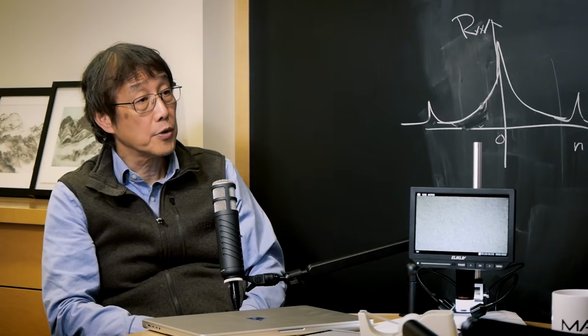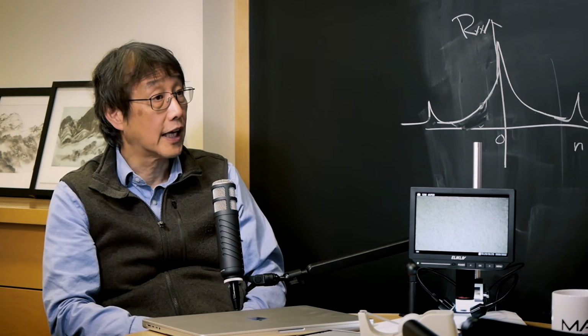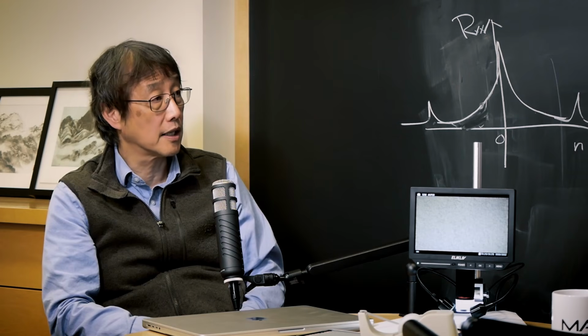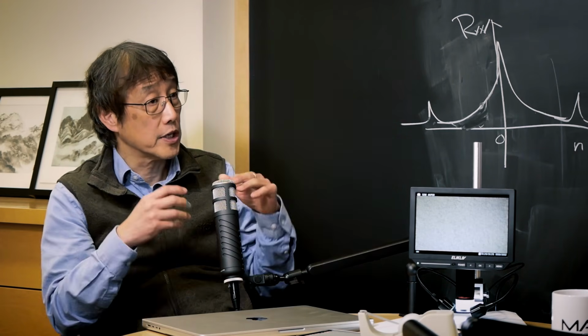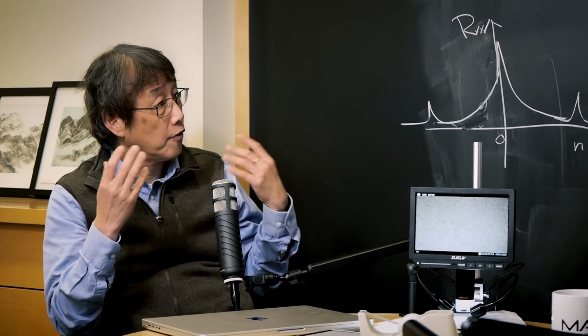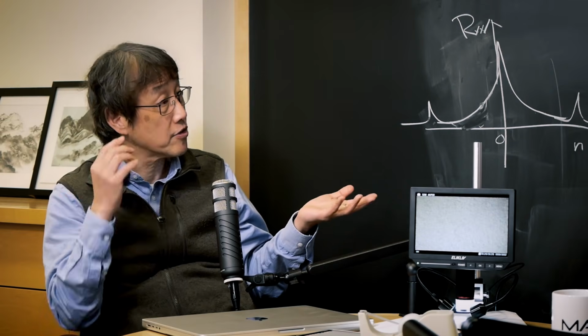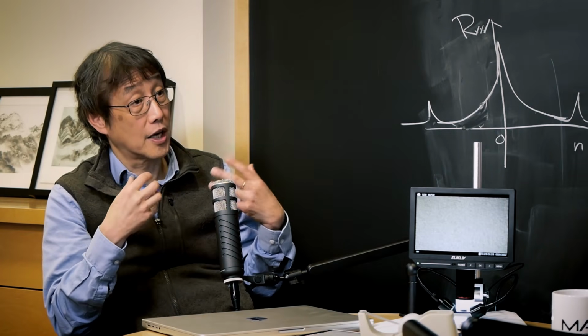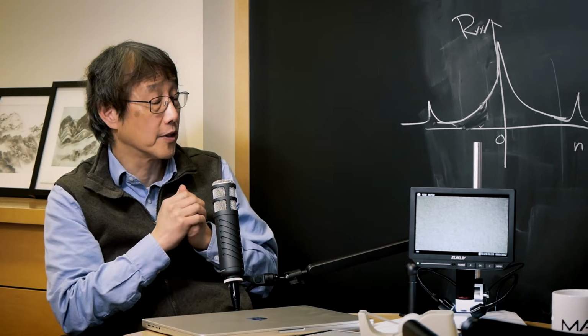Okay. And is there some intuitive way you could think of how that is conducive to forming Cooper pairs in the twisted system? Yeah, that is a really big question. I wish I knew. I think a lot of people have somewhat different ideas. As far as I know, there are two interesting schools out there. One is that, of course, it could still be electron-phonon, because the electron band got renormalized into a flat band, and the phonon band structures also changed. Because of this, there might still be very strong electron-phonon coupling, which allows the Cooper pair to form by phonons.